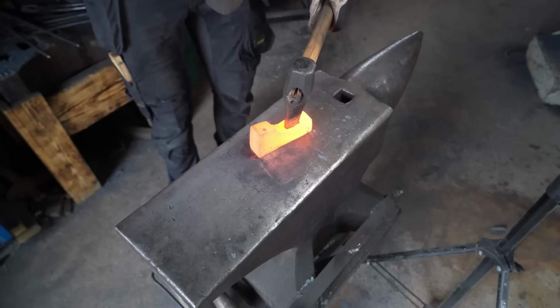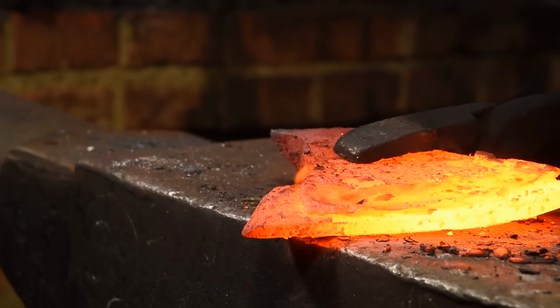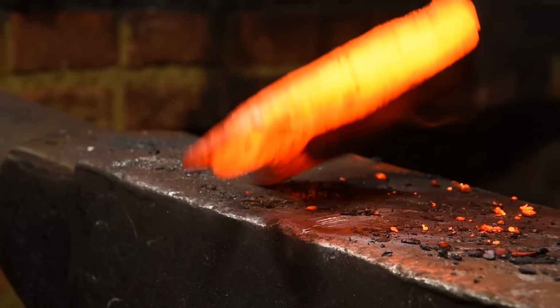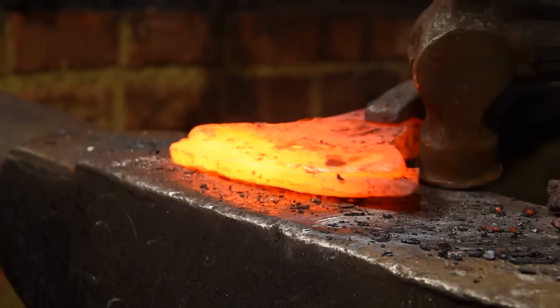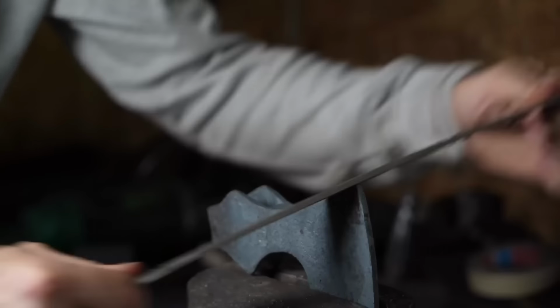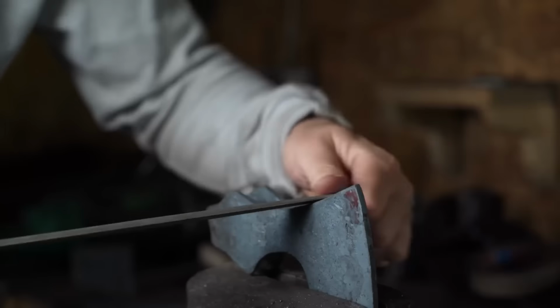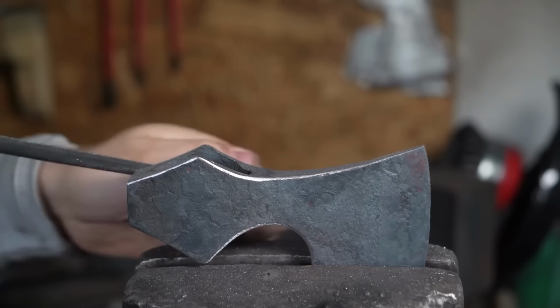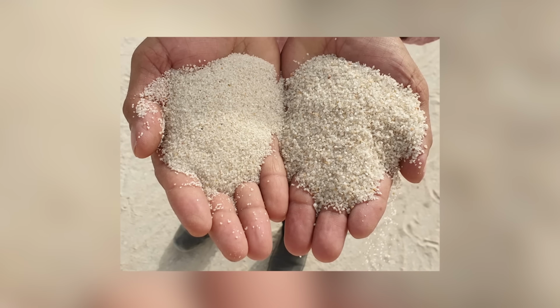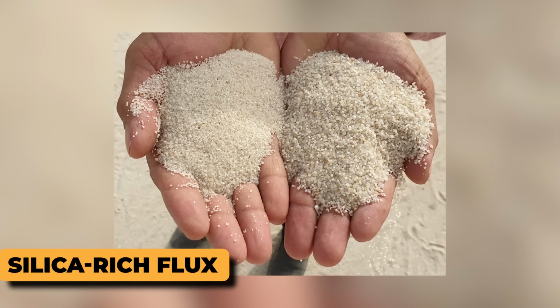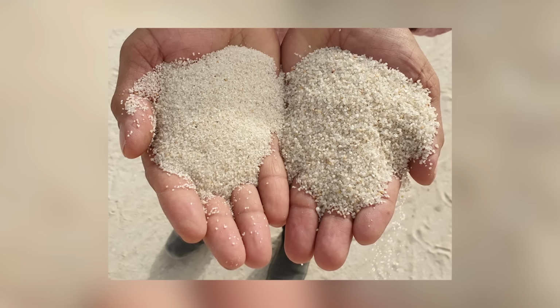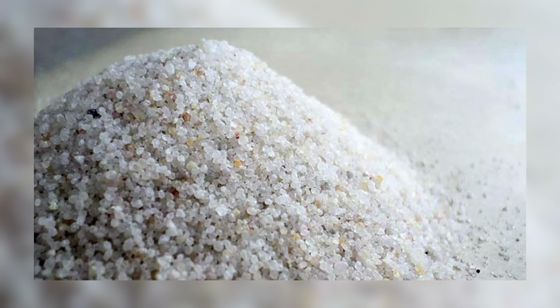If you saw sparks shooting like fireworks, you were oxidizing your future axe into useless flakes. Viking axe blades weren't just lumps of iron. The edges needed to be hard enough to cut bone while the body stayed tough and shock-absorbing. So smiths folded the blade over itself, welding layers together with silica-rich flux, an ancient flux that worked like sticky glass, binding metal into a single piece.